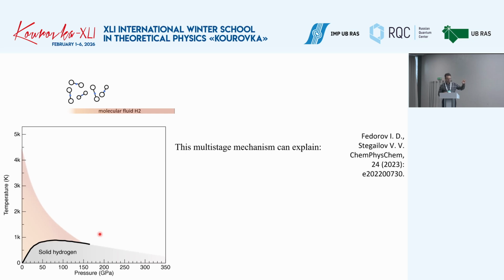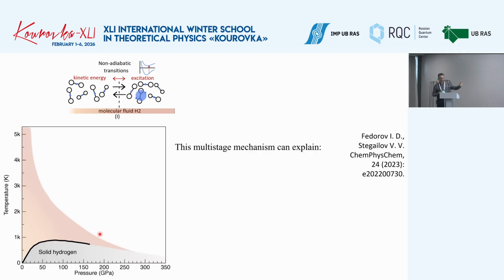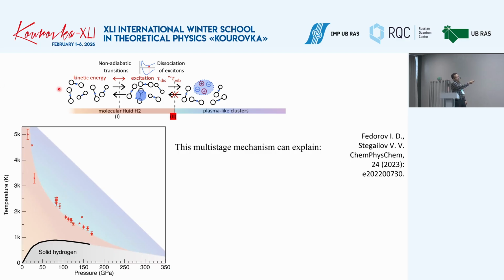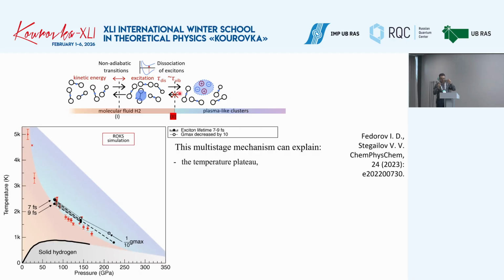On the basis of such a model, we can devise a mechanism of the transition for hydrogen. So first we have fluid at higher temperatures. Excitons form and disappear due to thermal fluctuations. At some threshold temperature, they begin to dissociate faster than they disappear, and this gives us some small plasma-like clusters in this fluid. And when these clusters form in different parts of the fluid in an independent fashion, the fluid begins to absorb light, and only after these clusters merge, the fluid begins to reflect light.